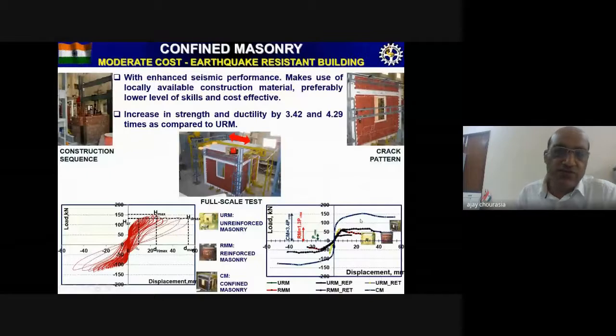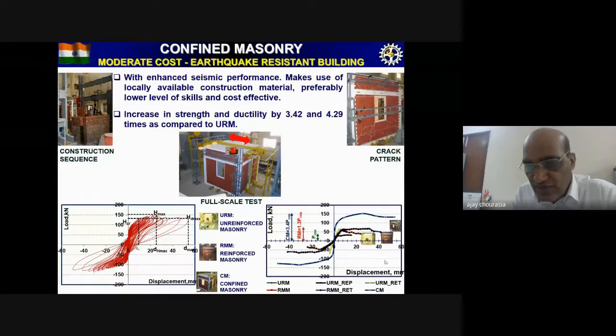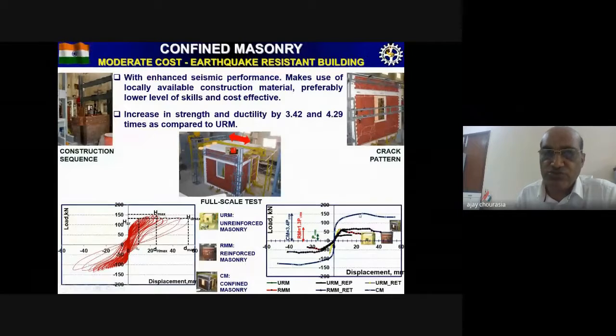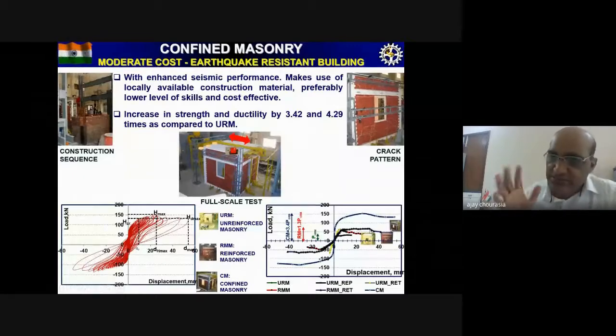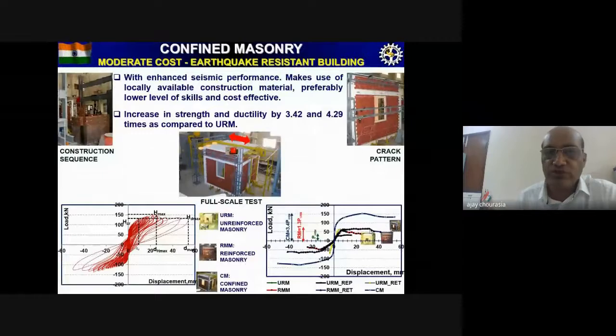Similar efforts were made while conducting the experiments on the unreinforced masonry and reinforced masonry buildings, and the same results were superimposed on this slide. That clearly shows the confined masonry building is 3.42 times stronger in terms of strength when compared with the unreinforced masonry, and 4.29 times better in terms of ductility when compared to URM buildings. Apart from that, the initial stiffness in the confined masonry is phenomenally high as compared with the unreinforced masonry buildings. That itself demonstrates that by minimal interventions, a great enhancement in seismic performance in terms of strength, stiffness, ductility, and damage pattern can be achieved.